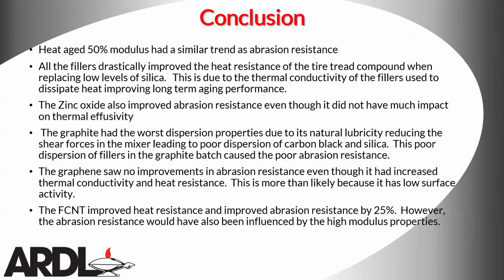So in conclusion, heat age 50% modulus had a similar trend to abrasion resistance when using your thermally conductive fillers. All the fillers drastically improve the heat resistance of the tire tread compound when replacing low levels of silica. This is due to the thermal conductivity of the fillers used to dissipate heat, improving long-term aging performance. The zinc oxide also improved abrasion resistance, even though it did not have much impact on thermal effusivity, but we did see a slight bump with thermal conductivity.